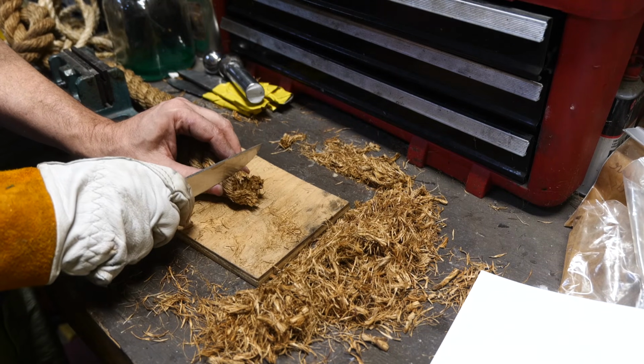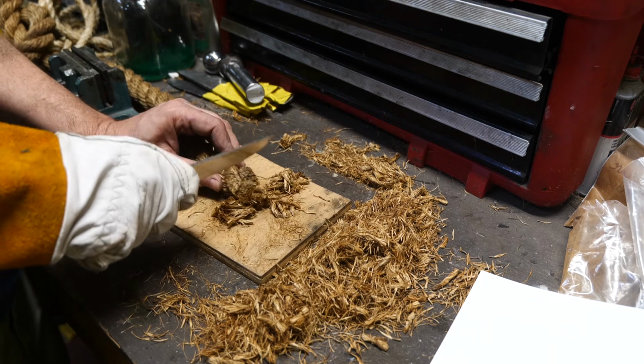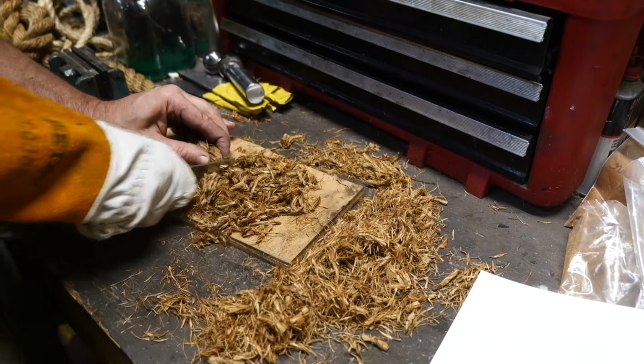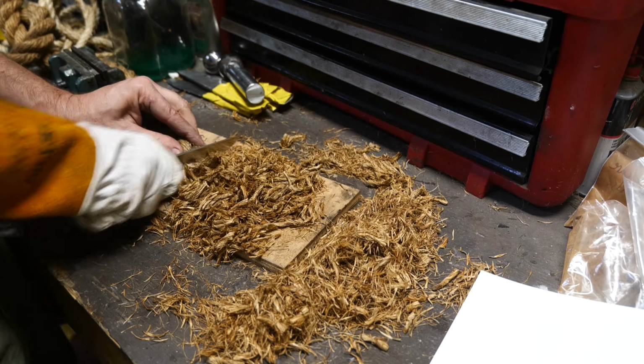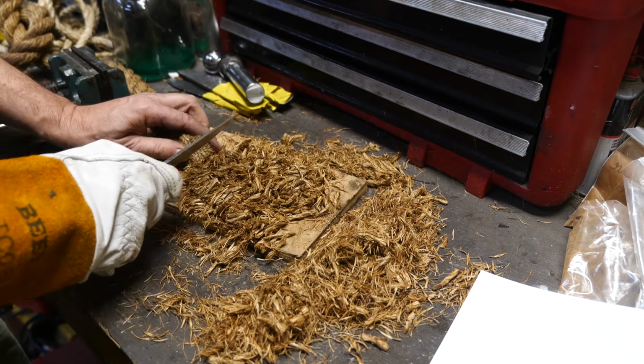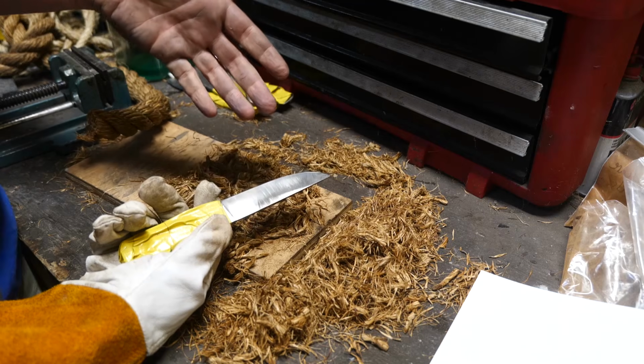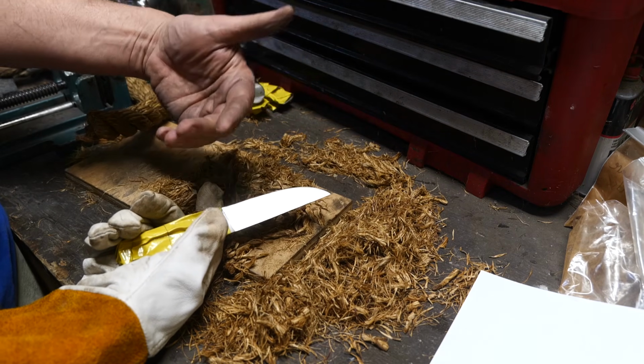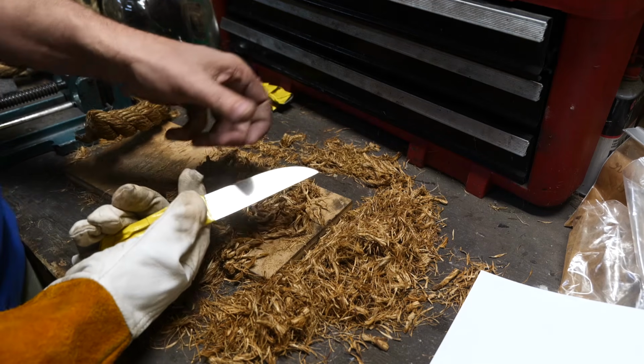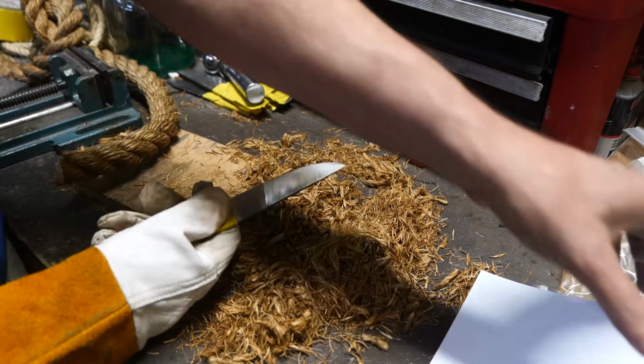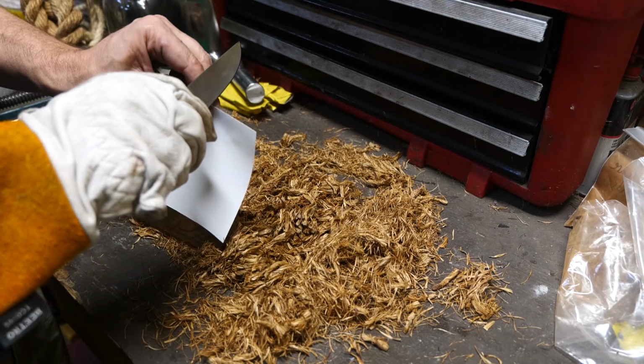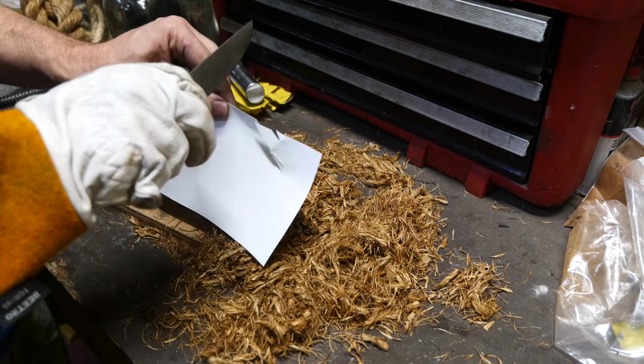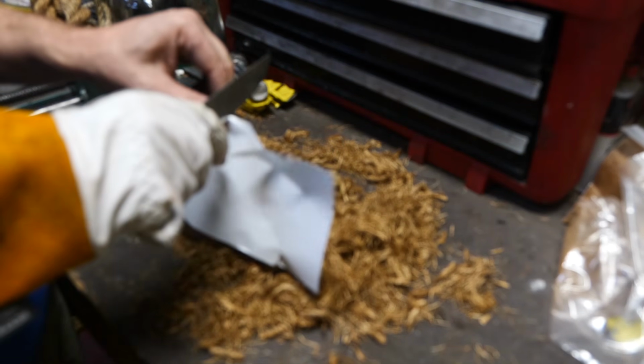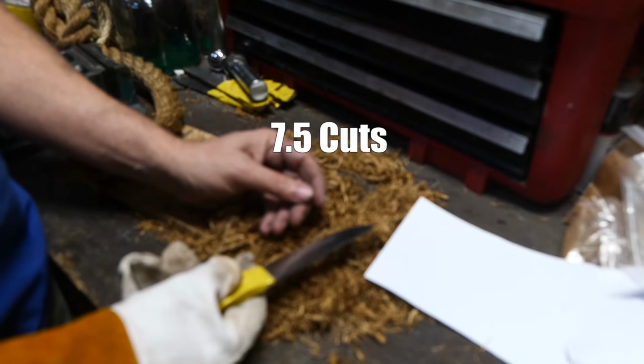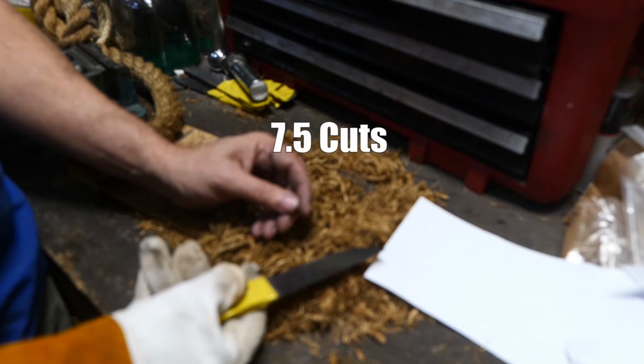Number to beat's 11. Ooh, I like that. All right, 8 cuts, it's really slowing down. Now remember, this was quenched from 1600 degrees. The higher you go on the quench, the more toughness, but the less edge retention, according to Larrin. So we're starting to get bogged down with 8 cuts. That's not a good sign. Let's check the edge here. Sorry, ran out of batteries there. All right. So probably actually went 7 cuts, maybe 8 cuts.